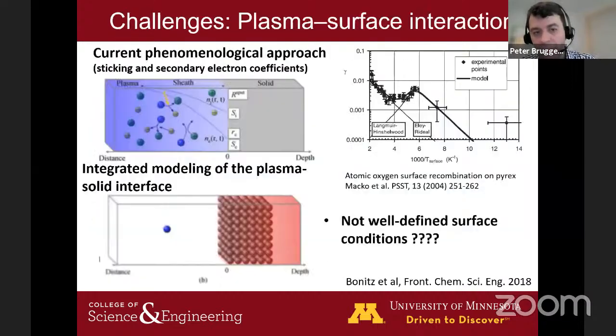And I think then from a materials point of view, really integrating plasma models with almost quantum models of materials and how processes are actually happening is another frontier that has been almost untouched. Plasma models now really have sticking coefficients in their models that are often estimated. Sticking coefficients are sometimes measured, but the accuracy of these coefficients is relatively low. In particular, when the interest becomes predictive modeling of surface processes, a better accuracy there would really go further, but again, would require a lot of insight into what really happens on these interfaces, combined with experiments as well.